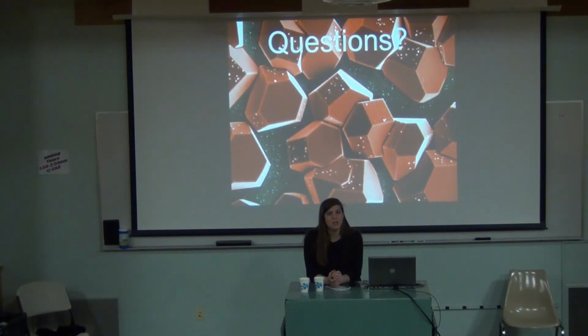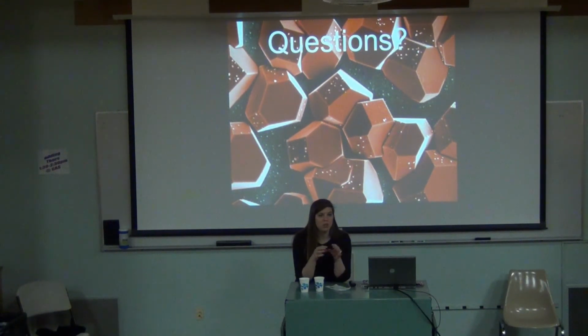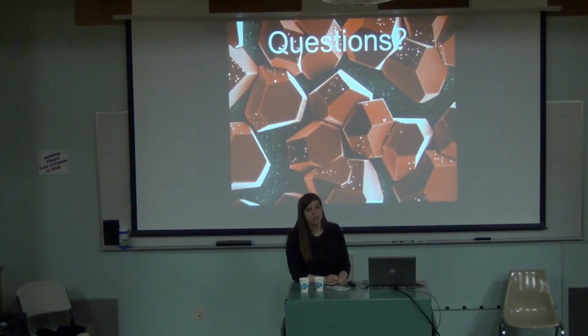I mean, you could do EDX and look over just one area and see if it was only platinum here and it was here. But if they were mixed together, like if you tried to put gold and platinum in solution and then shine the light on it, if they both still went on the 100 plane, you wouldn't really know which was which, right? Unless you did some element mapping with EDX. But with the electrodeposition, everything has a different reduction potential, so it would deposit as it reaches that point. So it wouldn't really make sense to have more than one thing in there because you'd have to do several different potentials for that to happen. And those things happen within like a second. I mean, you could electrodeposit gold in less than a second.